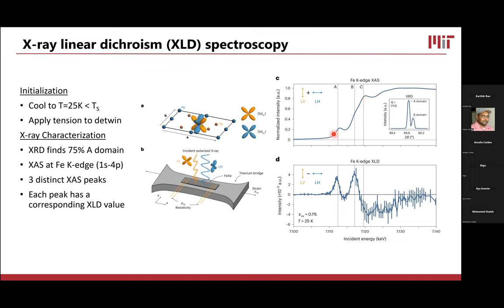But this feature A here is telling us something about the local hybridization of the P and D orbitals, which I'm about to show you. But first, I just want to point out that instead of taking the sum, if you take the difference of the two linear polarizations of the X-rays, then you get a plot that looks like this. So this becomes our XLD across the full energy scan. And you can see that there's a peak associated with A, B, and C here.